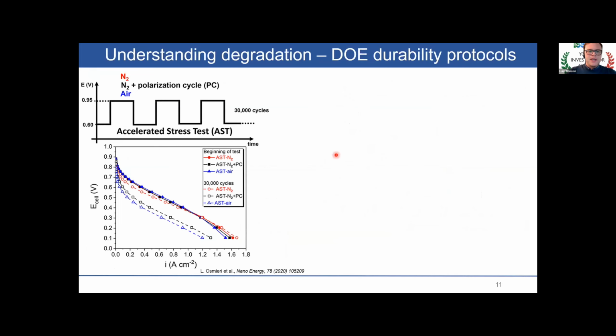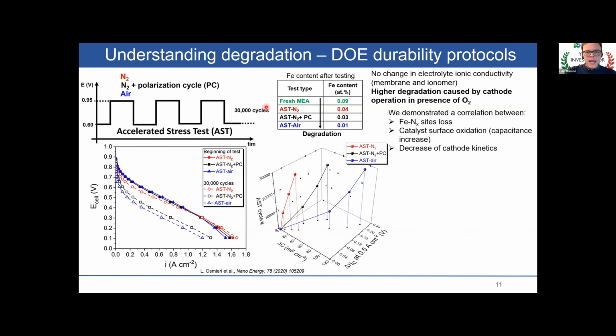Another very important aspect is the durability of these materials, which is challenging compared to the standard platinum catalyst. So I investigated several different accelerated stress tests in different conditions for these catalysts, and demonstrated a trend that correlates the higher degradation that happens when the cathode is operated in presence of oxygen, so when the ORR actually takes place, rather than in an inert atmosphere.